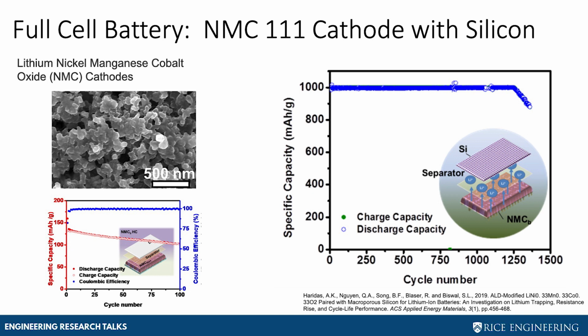We have gone ahead and put this into a full cell battery, so we've used high performance cathodes. So this is lithium, nickel, manganese, cobalt oxide cathodes that another very talented postdoc who came in was able to fabricate. She made them stable, and she showed that when she paired this with our silicon-based anode, she was able to get that capacity of 1,000 milliamp hours per gram for over 1,000 cycles. So this is a battery that you can imagine being able to see in one of your devices that now offers that extra capacity as well as cycle life.